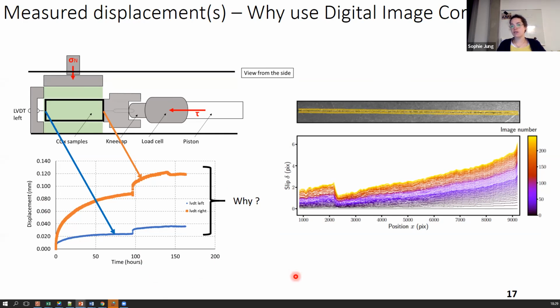This is why we use digital image correlation, because as you can see on the right side of the slide, with the digital image correlation, we have access to the whole fracture and what happens along the fracture. So here you can see on the graph, the different colors represent the time. At the very beginning, the line is flat because it's the beginning of the experiment. There is no movement, and little by little, you see that there is more movement on the right side, because it's where we are pushing the block, and you see that the movement is transmitted all along the fracture.